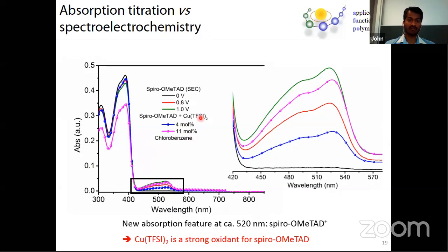So we took copper TFSI and added it to spiro, and then we compared those spectra with the ones from spectroelectrochemistry, the dotted lines here. Those are quite well matching with the electrochemically oxidized species. So now with confidence, we can say that copper TFSI has oxidized spiro-MeOTAD. It means that basically we are now able to p-dope spiro-MeOTAD with copper TFSI.